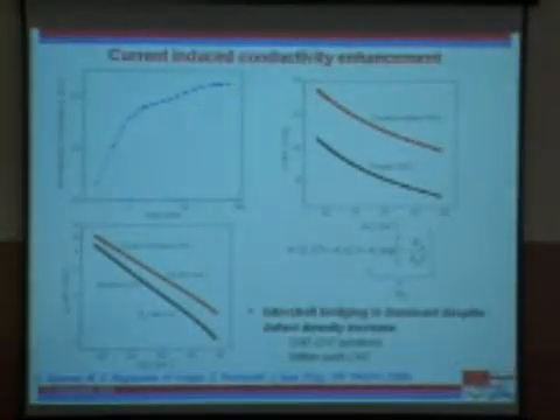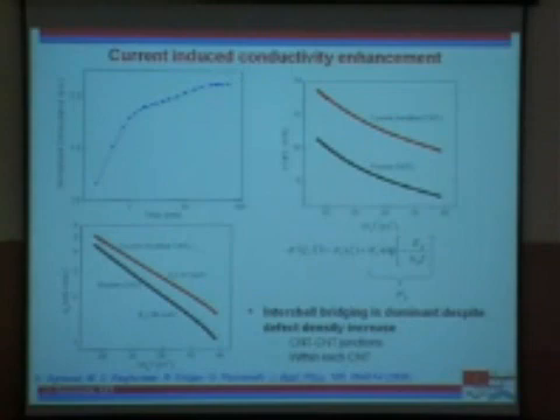And the very interesting thing here, though, is once you have these mats of nanotubes and you're passing high currents and you're creating sparks and you're breaking nanotubes and so forth, you would expect that the conductance will go down. Correct? But what happens initially is the conductance goes up in short time frames. And the reason for that is, even as you're creating defects, you're also creating more pathways for the current to be carried through in this network.